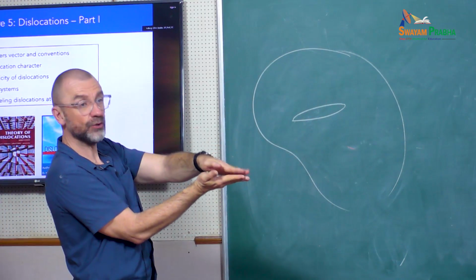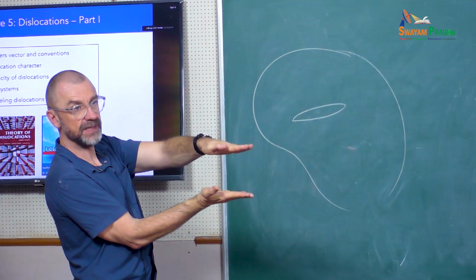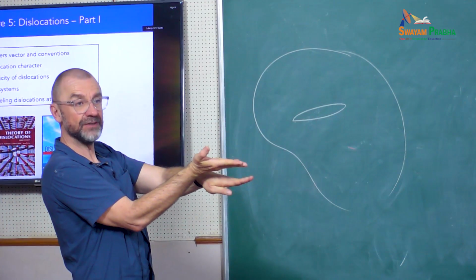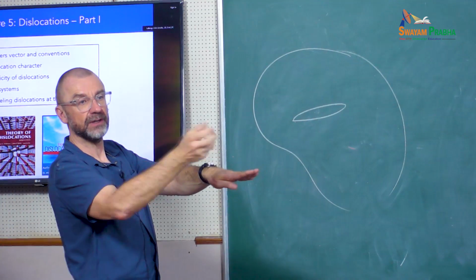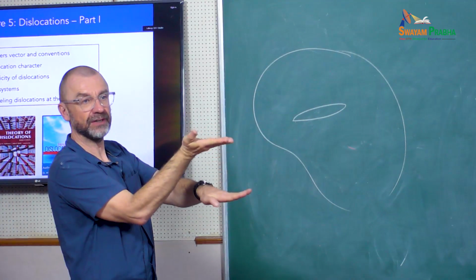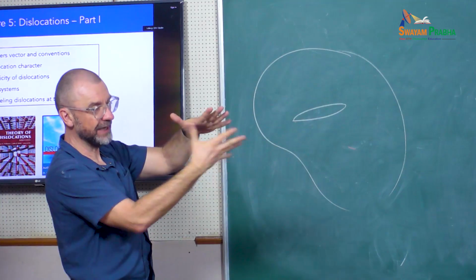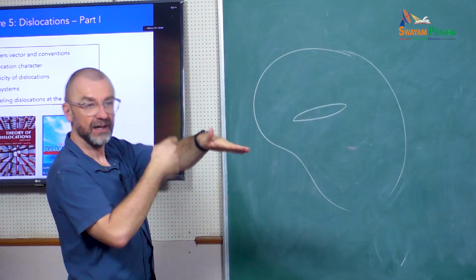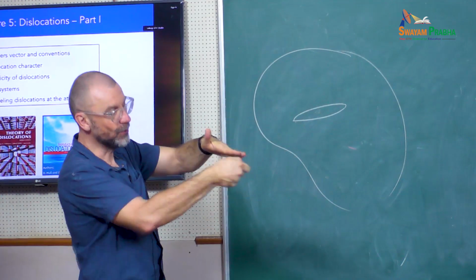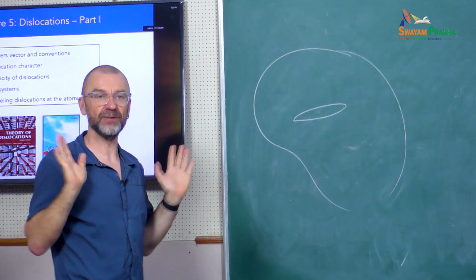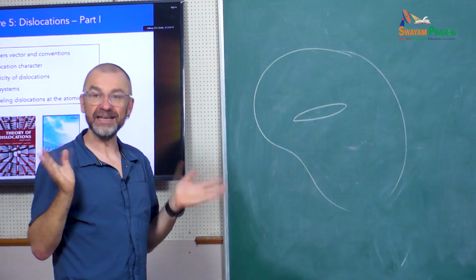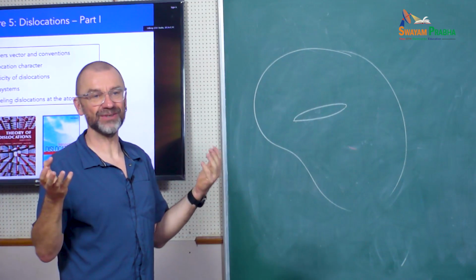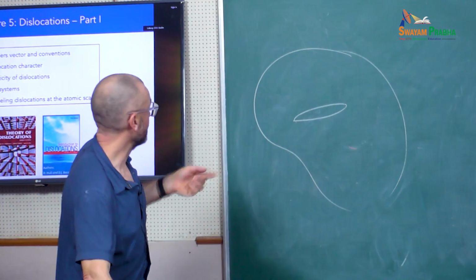If you have created a void by the displacement, you fill it with new material. If you have overlapping material, you remove the overlapping part. After that, you again have a continuous medium, but with surfaces. Now you come with your magic glue, you glue back the surfaces, and you let the system relax. What is, in that procedure, the dislocation? Where is the dislocation?